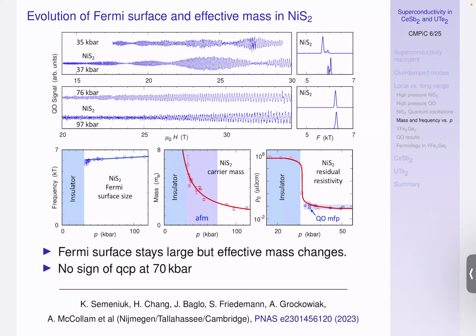But the carrier mass changes quite a lot. Near the insulator transition, it's about 6, and then it goes down to about 1.5 at 100 kilobars. So there's a strong pressure dependence. And then we also checked what happens to the mean free path and so on. And it's roughly constant basically once you're in the metallic state.